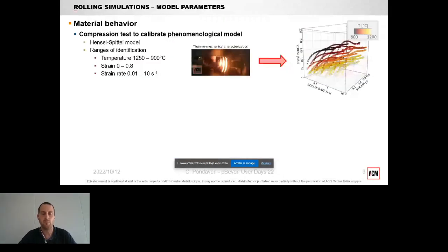So the different models and parameters used to perform a simulation are, first, the material behavior. So we use compression tests to calibrate a phenomenological model, which is a Hensel-Spittel model, with a range of identification in terms of temperature, strain, and strain rate that are representative of our forming processes.